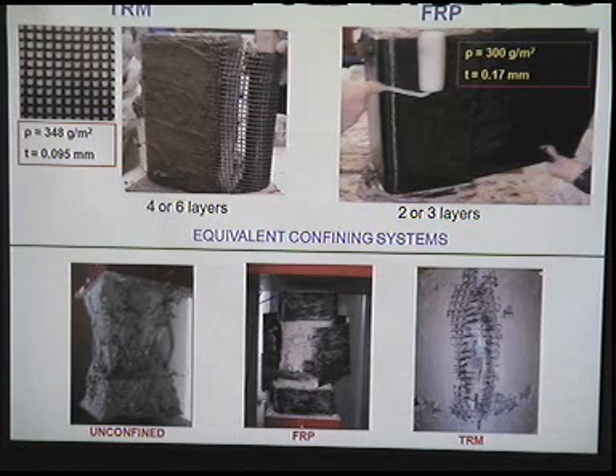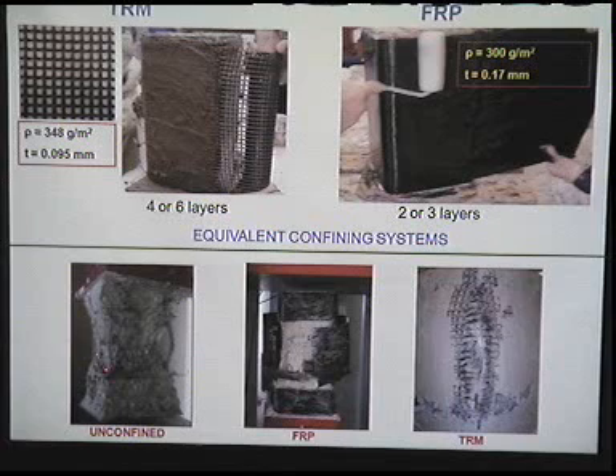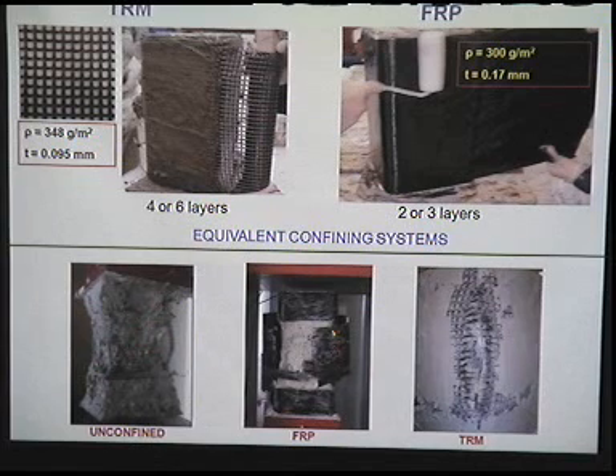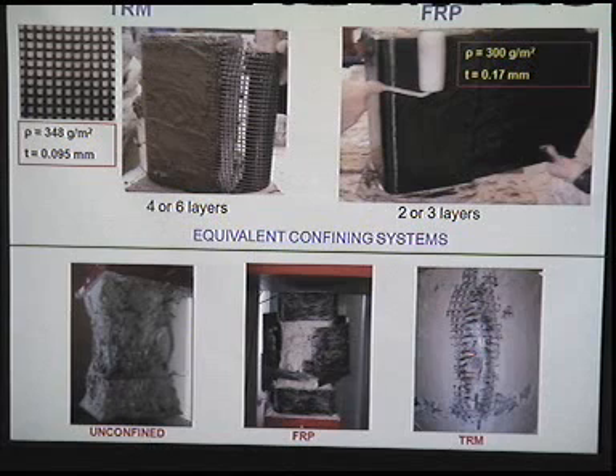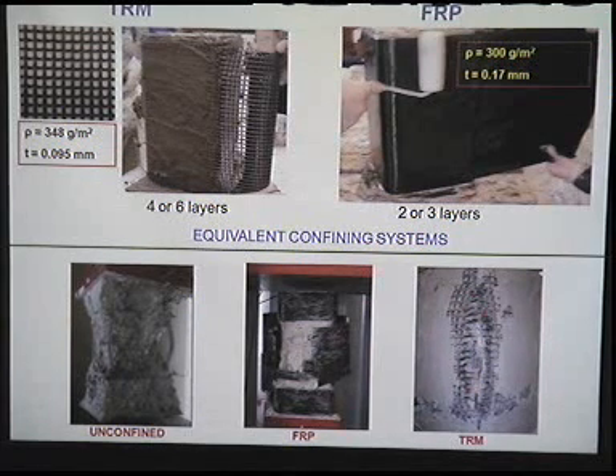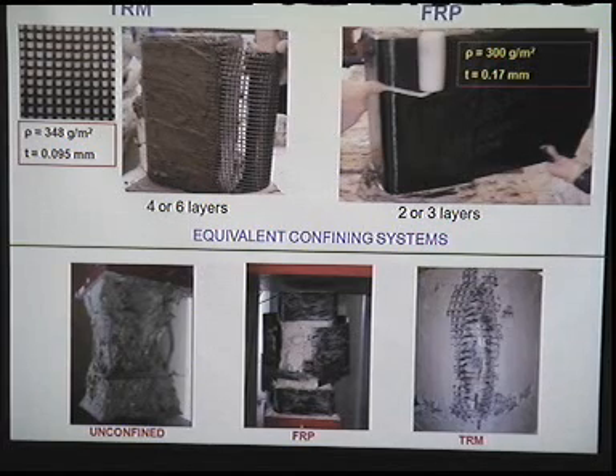And we started with uniaxial compression testing of those members. You see buckling of the internal reinforcement in the case of the unconfined members, and fracture of the FRP, but also of the TRM jackets in the case of confined specimens. The fact that we have this fracture is the best proof, actually, that the materials are fully utilized, that we can utilize the full strength of the fibers.